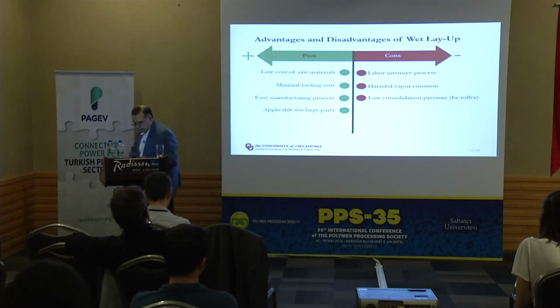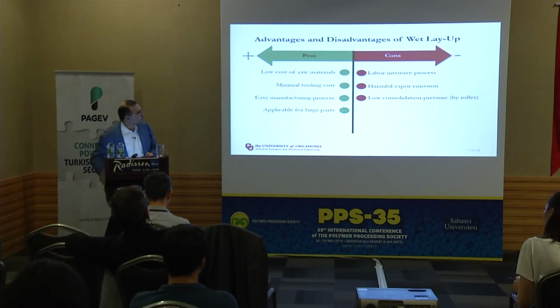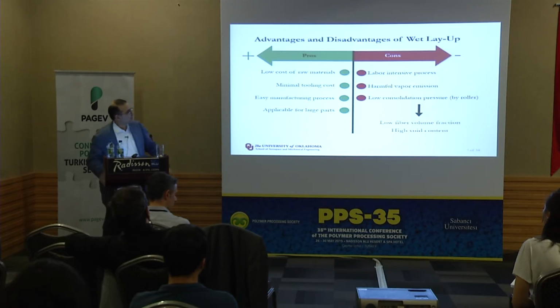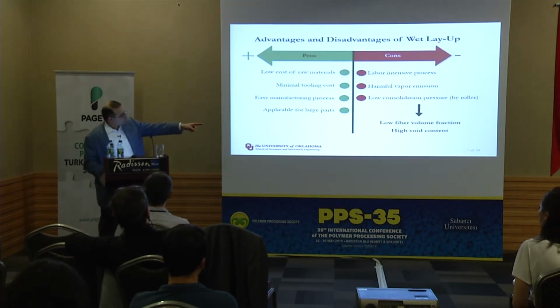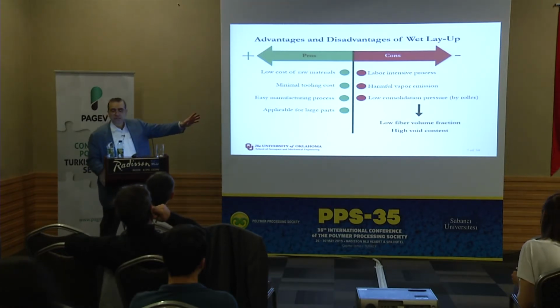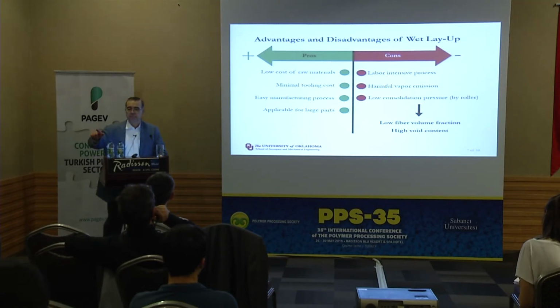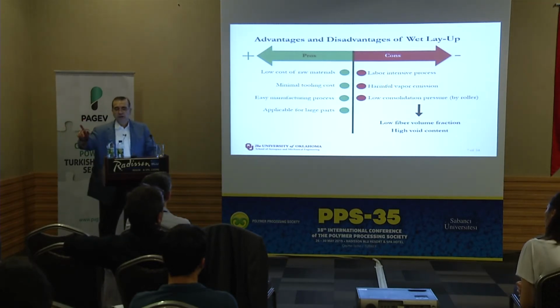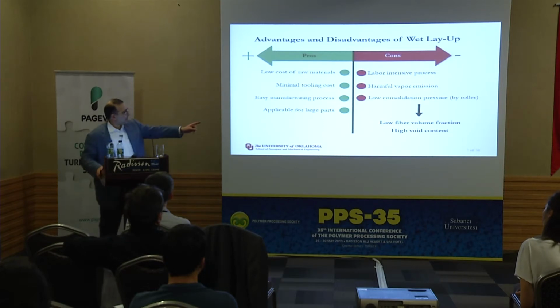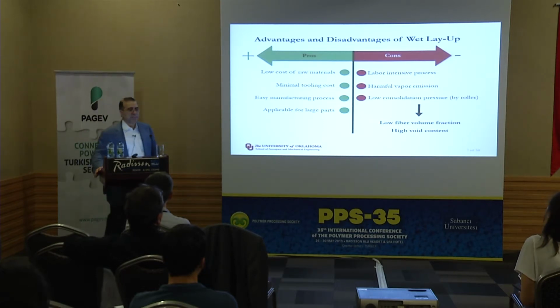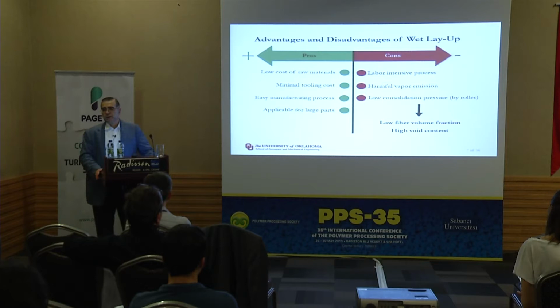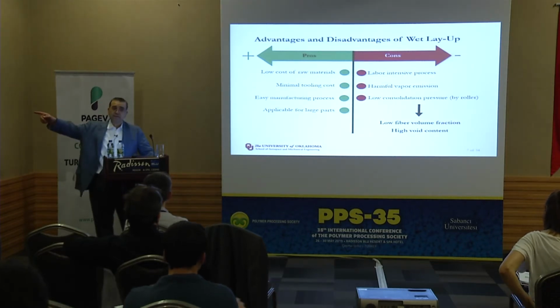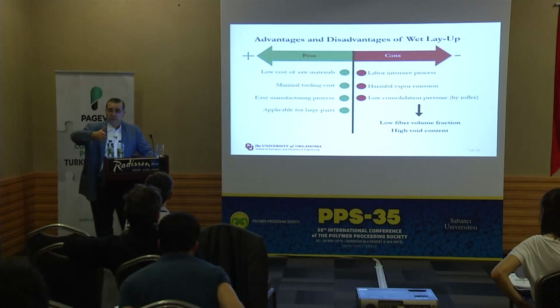So that will not get rid of voids. Your product will not be really good quality if you do a hand layup. There will be voids, high void content. I would guess that you will have 5% or higher voids, maybe 10%, 12%, and your fiber volume fraction will be 20%, 25% with hand layup. 25. Autoclave, remember, 65%. There's a big difference, 25 to 65.